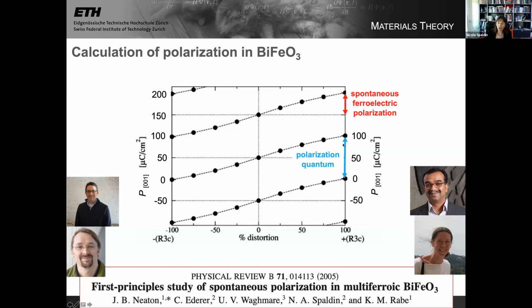Here's the polarization quantum. This is the charge times the lattice vector divided by the unit cell volume. And in this case, it's about 100 in these units, microcoulombs per square centimeter. Okay, so that's how it looks when you go and make a density functional calculation of polarization for a bulk periodic solid. Okay, a couple of things I want you to notice.